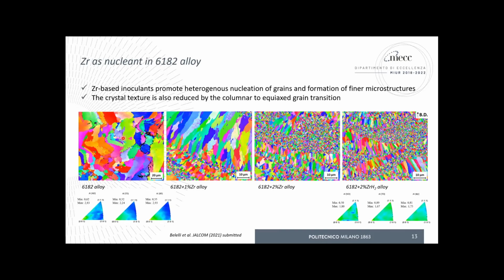The standard non-modified alloy produces quite coarse grains, some cracks, as already anticipated, while by adding zirconium 1% rather than 2%, we can promote a shift from columnar to equiaxed grains. We can understand that the shift is not completed yet. Okay, still there are some regions where the grains are not exactly equiaxed, but at least we can remove the crack. We can avoid the hot cracking phenomenon.